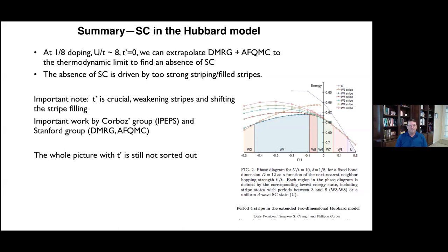Okay. But an important point to note about this, and this involves work by other groups, is that the role of T prime is crucial. And it's also, I would say, not really understood. There are particular nice calculations, but the whole picture is still difficult to understand. But T prime certainly weakens the stripes, and it tends to shift the stripe filling, as shown in this recent iPEPS paper by Philippe Corboz and his group, where these different W are stripes with a width 4, stripes with a width 5.